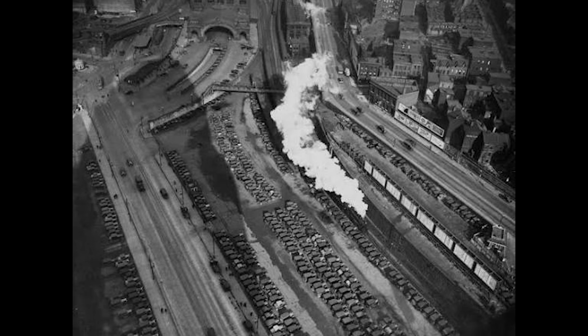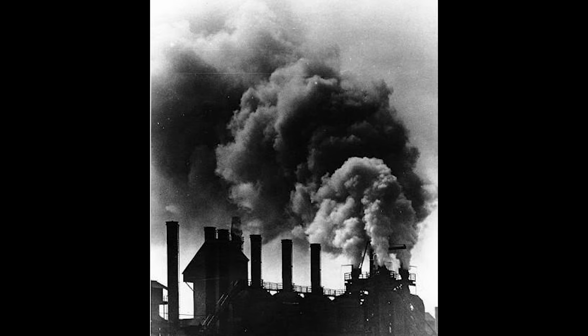By 1943, the American steel industry faced a crisis of quality rather than quantity. Production had increased exponentially, from 66 million tons in 1940 to 88 million tons in 1943. But armor plate rejection rates remained stubbornly high. Ballistic Research Laboratory at Aberdeen Proving Ground, Maryland, conducted testing on armor samples from multiple manufacturers. Tests revealed disturbing patterns. Some armor plates suffered from pitting, surface irregularities that weakened the steel locally. Some plates developed shrinkage cracks during casting, internal voids where the steel contracted unevenly as it cooled. Some plates failed heat treatment, emerging too soft or too brittle.